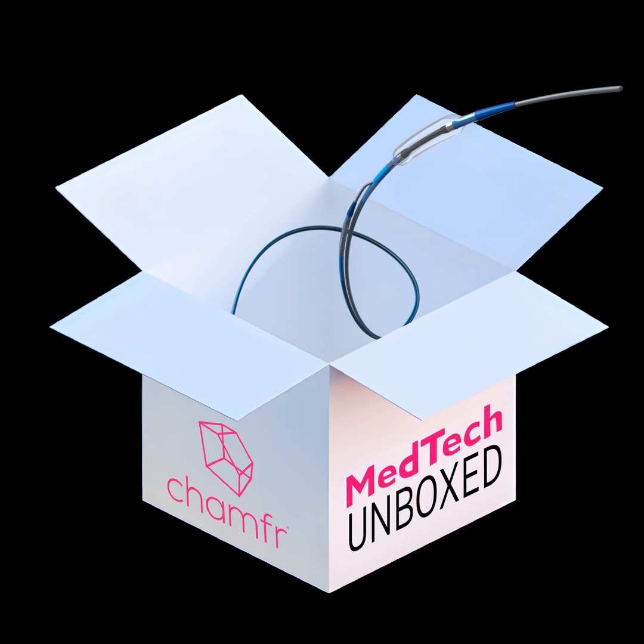So it could happen, let's talk an extreme. Say we just hit this thing really, really hard, we get to fill and then back off. It'd be a horrible process, but in theory you could do that. What might happen is while you're at that really high pressure, you get really good pack out right here, but then you let go and what's in there will still freeze, but now you haven't packed it. And so as it freezes, the stuff that's further down near the gate doesn't pack out as much. So it's less dense, so it shrinks more. And maybe you hit your diameter up here, but you didn't hit it down here because you cut the tool with a constant shrinkage rate. So those are things we're playing with.